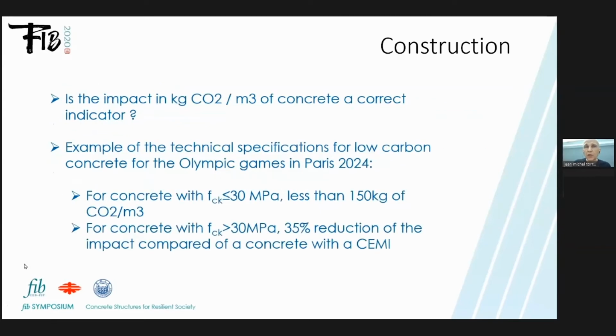We have to look at the indicator. What is a correct indicator for concrete? For the impact, it is kilograms of CO2 per cubic meter. And for instance, in France, we have an example of a technical specification for low carbon concrete for the buildings of the Olympic Games in Paris. They ask, when the strength is lower than 30 megapascal, to have less than 150 kilograms of CO2 per cubic meter. And when the strength is larger than 30 megapascal, to have a 35% reduction of the impact compared to a concrete with the same strength.